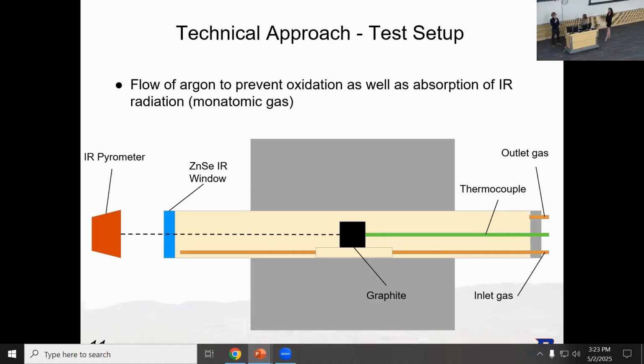The reason we're using argon is graphite will oxidize around 400 to 500 degrees Celsius, so we want to make sure that our graphite still remains and we don't open it to find nothing at these elevated temperatures. A unique property of argon gas is that, due to its monatomic structure, it is incapable of absorbing the IR radiation. On the left side, we can see the IR pyrometer looking through a zinc selenide window into our sample. We chose zinc selenide because it has a constant transmission across the 8 to 14 micron wavelength window, which made our calculations much easier versus, as we saw on Lauren's side, the high variations in some other transmittance curves.